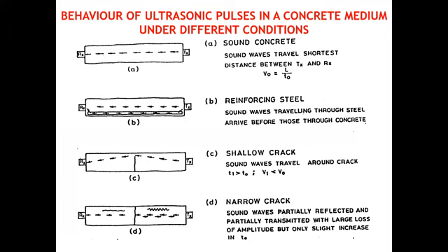So you need to use a profoscope and avoid the rebar locations, so that you don't get a value which does not actually represent the quality of the concrete. If it is a shallow crack, the waves will travel through an alternative path, it takes a longer time, and the velocity will get reduced. If it is a narrow crack, some of the waves are partially reflected and otherwise transmitted, so you get an unstable reading. If a crack is wide, obviously the whole wave will be reflected, and you will not get any signal at all.